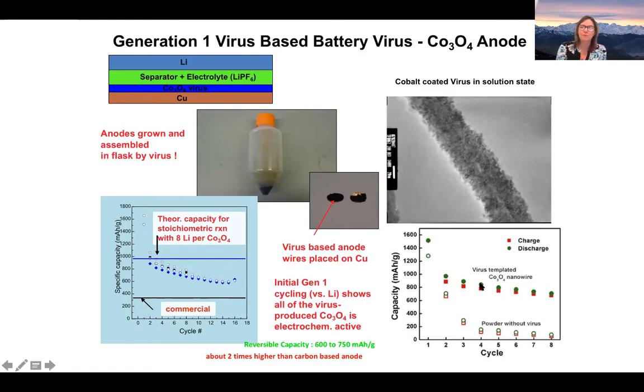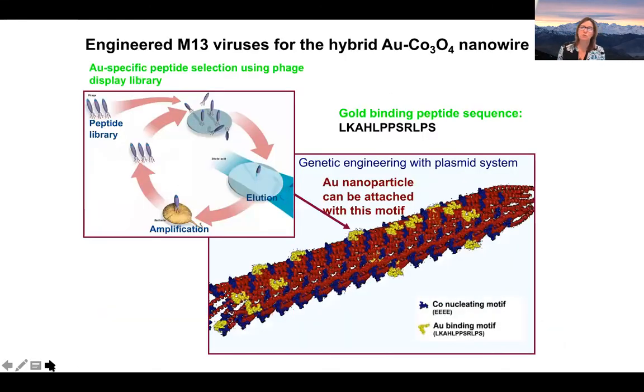And in this graph over here, we're looking at our virus templated nanowire versus just precipitating cobalt oxide out of solution, and it's not very effective at all. So we actually showed that it was about 2 times higher than a carbon-based anode, and carbon-based anodes are common anodes used today.